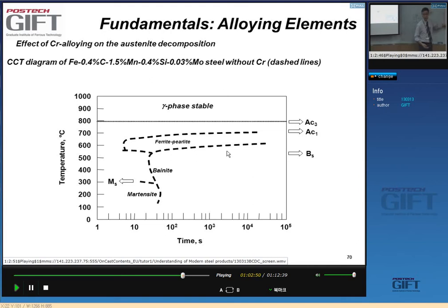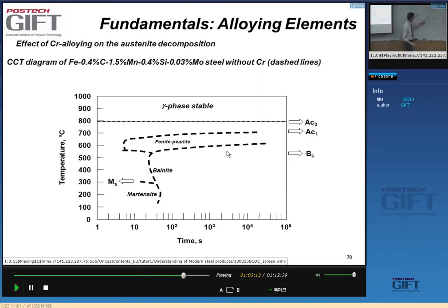Say I have a very high cooling rate. Yes? So again, I get a curved line that goes like this. And in this case, I cross this line here. It means that nothing happens until I hit this temperature and I form martensite. Basically, the diagram is just a way to tell you, well, somebody looked at the microstructure at different cooling rates, for this particular composition, and they packed all the knowledge they had about the transformation and the microstructures into this single diagram, yes?